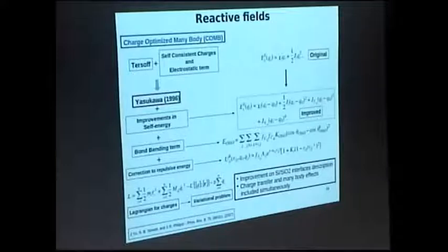That is something that is not so simple. The idea is the following. If you have in a system atoms that have different electroaffinity, you know that if they are bonded, you have some kind of charge transfer from one to the other. And in the potentials that I discussed until now, it was not taken into account. Then you can make some mistakes in some cases, right? And you cannot describe polarizabilities also for the systems if you have something that ignores the charge.